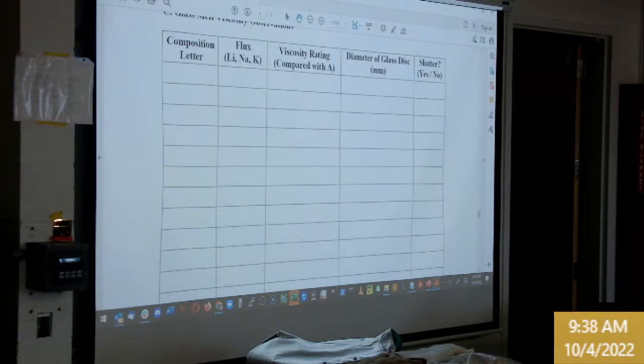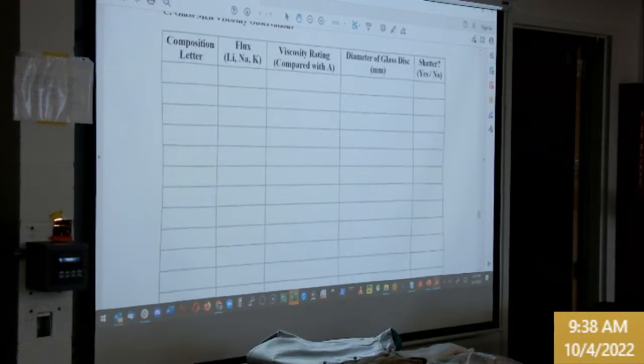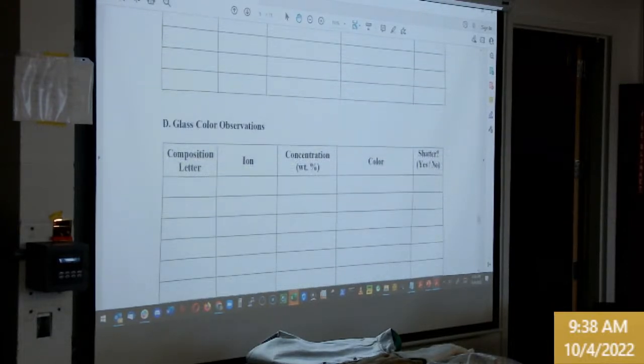Viscosity rating, you can say lower or higher. You can rate them 1 through 5 or 1 through 10. It's kind of up to you, but try to come up with a semi-quantitative way to rate viscosity. The diameter of the glass discs, we'll have basic rulers. Some people like to use their own calipers. That's also fine. But to the closest millimeter is probably all you need. Whether or not it shatters, that of course can make the diameter measurements a little bit of a challenge depending on when we take the measurement. But if it shatters, it's no big deal. Put a dash, describe what happened. So this is more of the physicality of the glass that we made. And then there's another table with